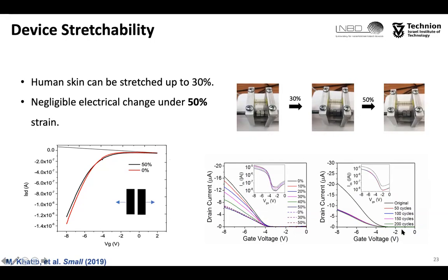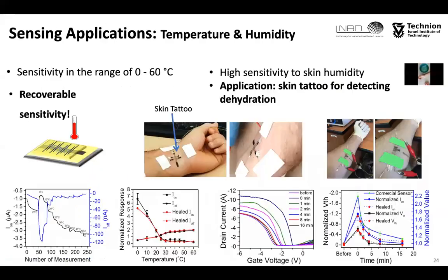You can see that we have tried this stretching back and forth 200 cycles, and you can see that in many cases we got very nice results and repeatability and reproducibility with this device. And as could be seen here, the device could work on detection of a wide variety of temperatures, also on pH, again, by defining the chemistry on the surface.